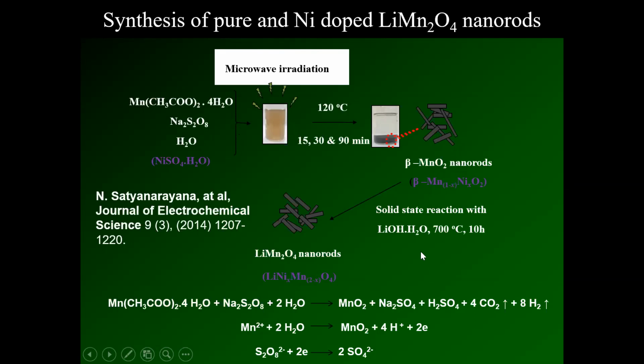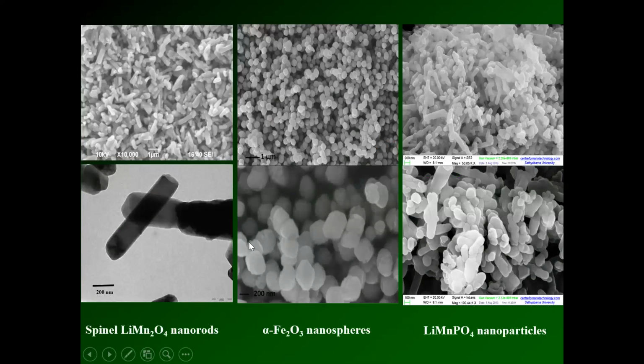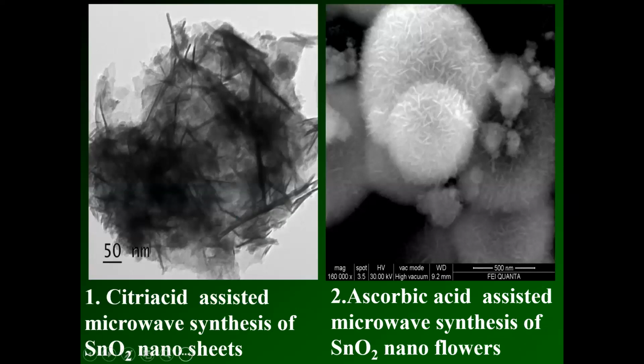Then we add lithium hydroxide to these nanorods and do the solid-state reaction. Just heat it, and lithium diffuses into the nanorods and forms lithium manganese oxide nanorods. So we have developed spherical and rod-shaped materials under different conditions using the microwave hydrothermal method. You can see spherical, small rods, mixed and pure ones. You can get lithium manganese phosphate and lithium manganese oxide in different shapes. And here, SnO2 nanoflowers, nanoflowers and nanosheets.